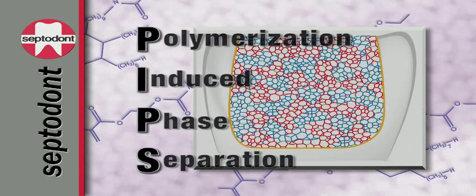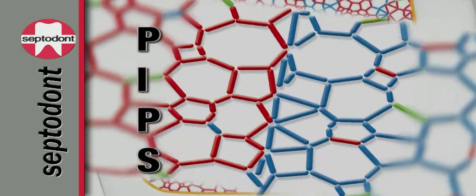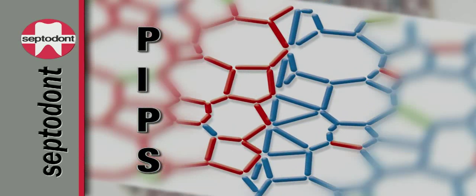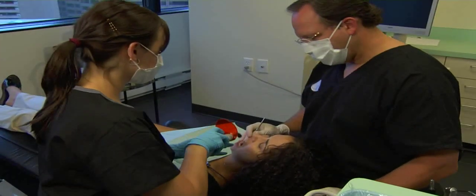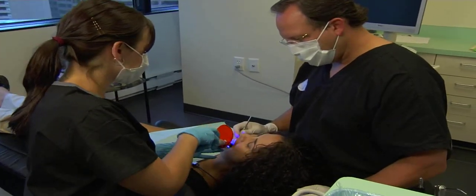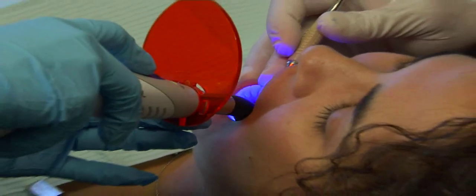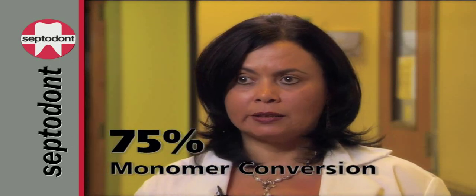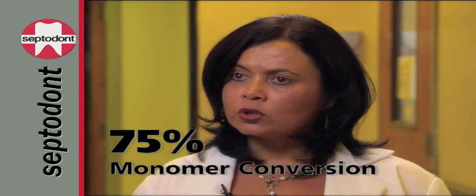When using PIPs, it's challenging to keep the separating phases at the microscale so that the translucence is not affected. A decrease in this translucence will compromise not only the final aesthetics but also the penetration of the curing light and the polymerization efficiency. Endurance shows a conversion of its monomer into polymers of 75%. This high conversion produces greater strengths and decreased potential for unreacted monomers to be extracted from the composite.